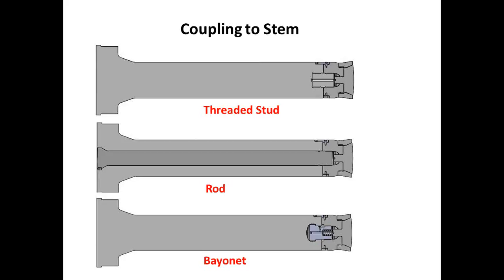What we started doing next was attaching the dummy block to a threaded rod which went through the stem. The rods in most cases floated, so this prevented us from putting excess pressure on the threads. The problem with both of these is we want to make sure the dummy block, when it's used, is about billet temperature. And if we're threading a dummy block that we hope is about 800 degrees onto a threaded stud or rod, it's going to be extremely uncomfortable for the person installing the dummy block. There's several of us that started using bayonet studs, and one of the main reasons to use a bayonet stud, so it was easy to put a hot dummy block onto a hot stem.